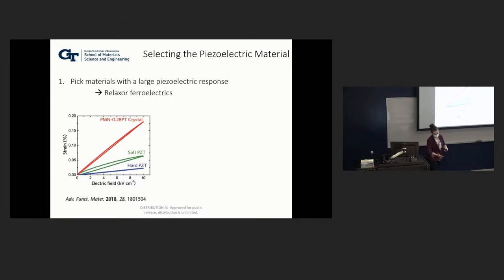The piezoelectric material. Now the first one is, let's pick a piezoelectric material with a large response. This is not deep advice, right? This is not complicated, but this is where we started. So we first look to relaxor ferroelectrics. Relaxor ferroelectrics are a very particular type of ferroelectric material that has a very, very large piezoelectric response. So in this case, what we're looking for is, for a given applied electric field, we want to get the most strain out as possible.